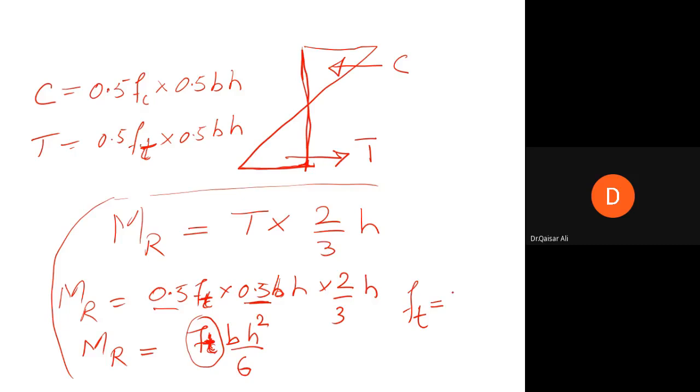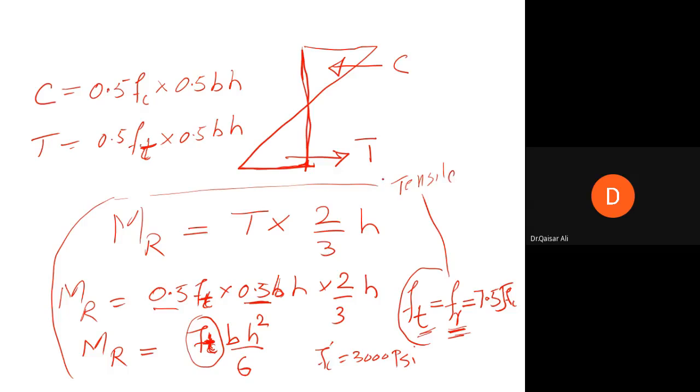और वो टेंसाइल स्ट्रेंथ हमने, अगर आपको याद हो, पिछले एक्सपेरिमेंट में मालूम की थी, वो FR था। ACI कोड आपको डायरेक्ट कहता है कि अगर आपके पास स्ट्रेस डेटा ना हो, तो आप इस FR, विच इज FT, द मैक्सिमम टेंसाइल स्ट्रेंथ, 7.5 टाइम्स FC प्राइम स्क्वायर रूट से मालूम कर सकते हैं। आप मुझे एक कंक्रीट है जिसकी स्ट्रेंथ FC प्राइम 3000 PSI है, इसकी FT या इसको टेंसाइल स्ट्रेंथ या मॉडुलस ऑफ रप्चर कहते हैं, ये मालूम करके बताएं। मैक्सिमम फ्लेक्सर टेंसाइल स्ट्रेंथ, flexure tensile strength, or this is also called as modulus of rupture.